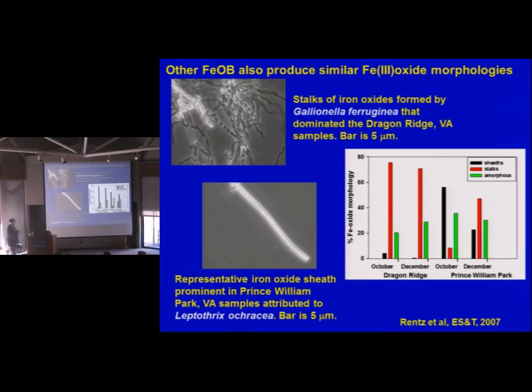And Jeremy Rentz figured out what's the percentage of oxide morphology from sheaths, what's the percentage from the stalks, and what's the percentage from amorphous. So you could actually get an idea of the relative oxidation rate from that characteristic. Now, that was all done by microscopy, but gives you an idea. And you'll notice there's a variability. Notice that the sheaths were very low in this case for Dragon Ridge. Notice that in this case, they went down, but they were still measurable.